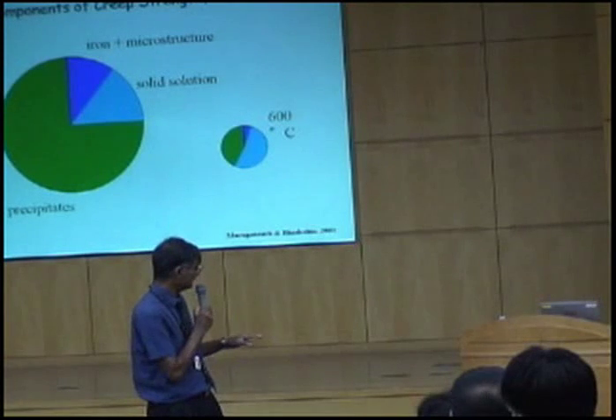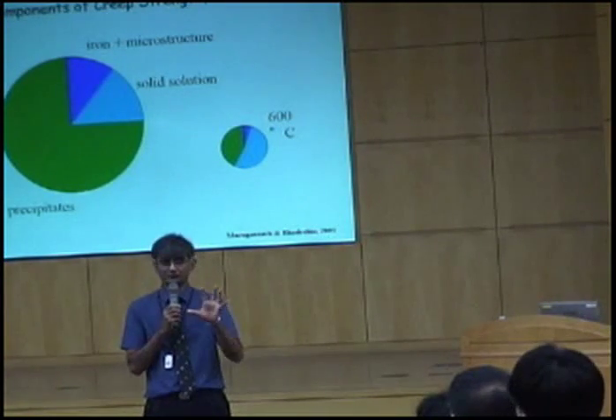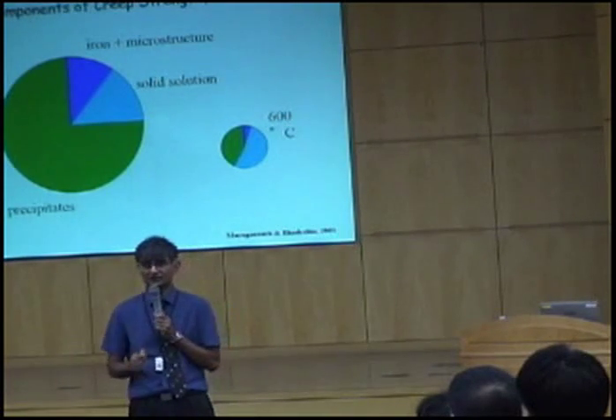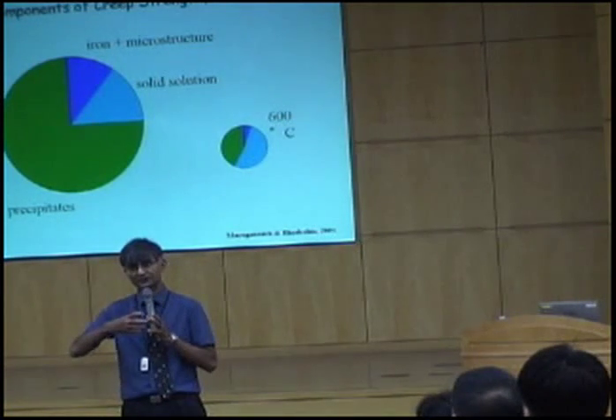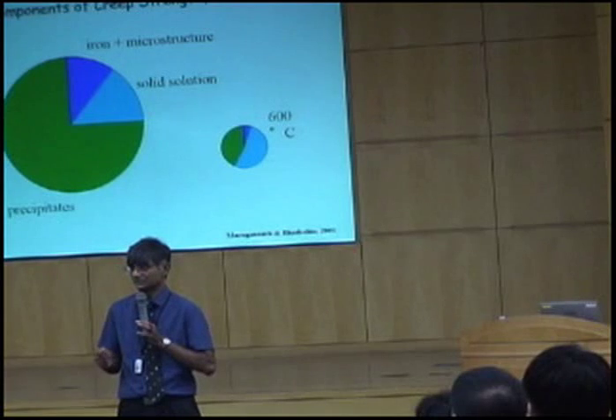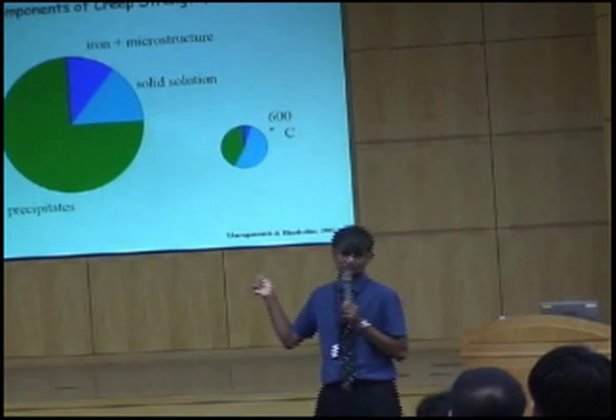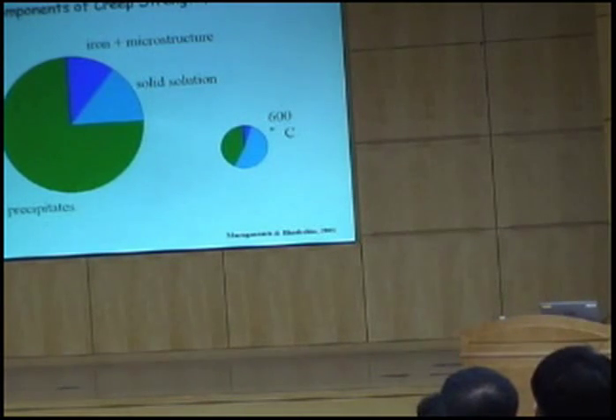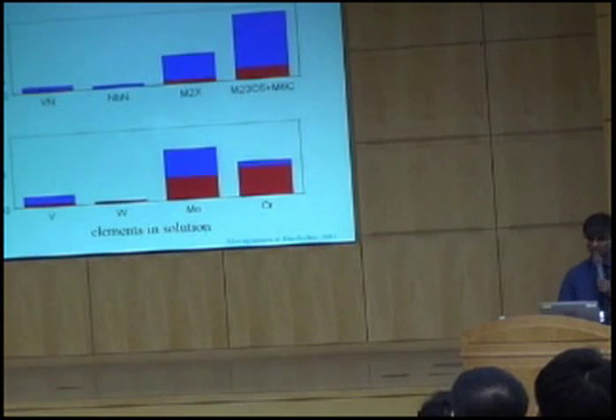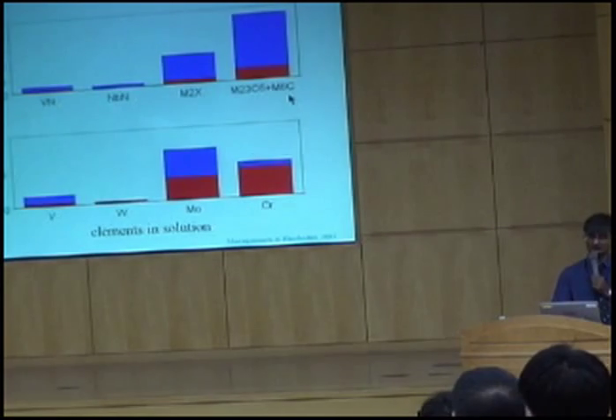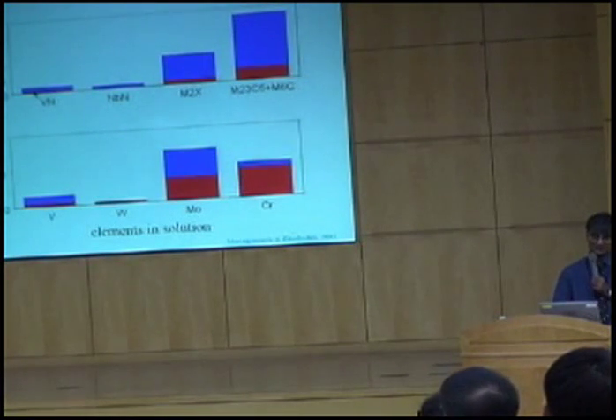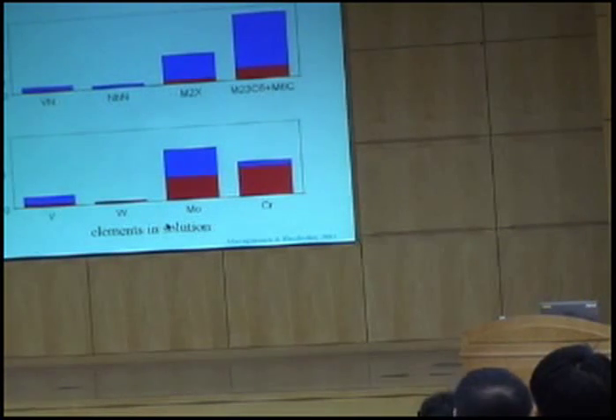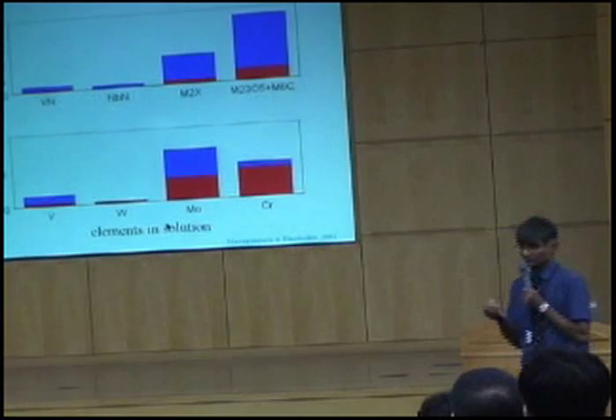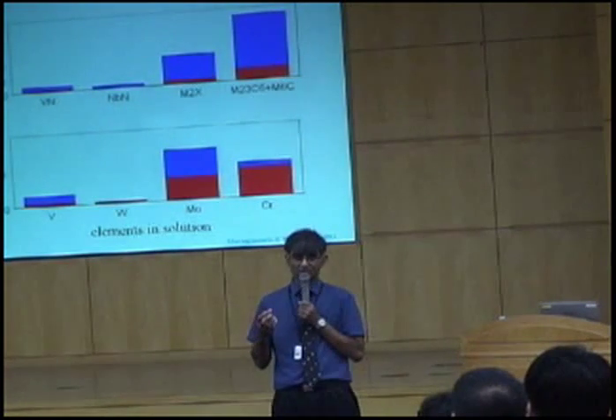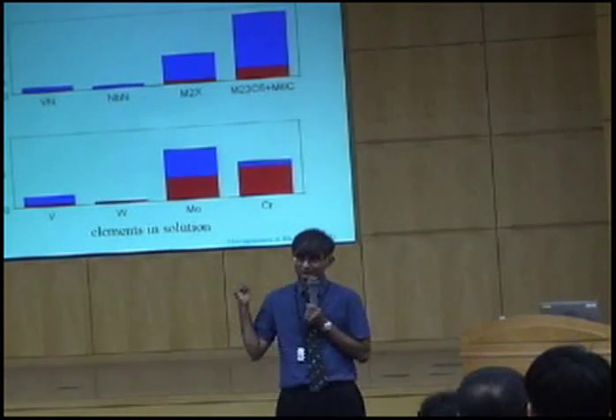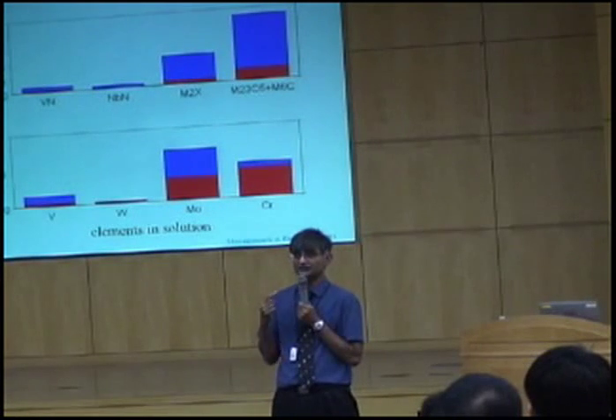So what we are doing here is using neural network models to capture the behavior of creep-resistant steels. And these graphs that you see on the screen are actually produced using neural network models, where we can deconvolute the components of the creep strength of complicated steels. There is a very large number of variables involved in determining creep properties. Using this method, we can even say that this much of the strength comes from M23C6 and M6C carbides, from niobium nitride, vanadium nitride, and from solid solution strengthening, and so forth. So even though we don't have the fundamental theory for creep which is capable of predicting the creep strength, there are other methods we can use to study the creep strength of complicated steels and to make predictions.